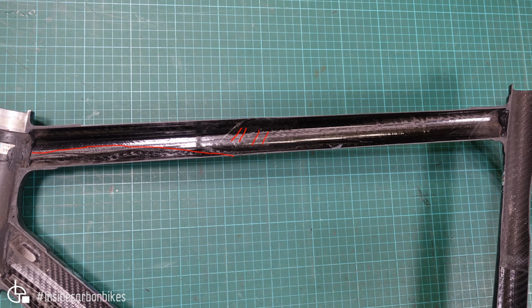In our experience, we see damage to the top tubes. That's the main damage that we see on these bikes. We don't often see damage to other areas of the frame. It's mainly the top tube, and whether they're using a different resin system, a non-toughened system, or whether it's a little bit resin rich or something like that, it just seems that the top tubes are a little bit more susceptible to damage than the other tubes on the frame. So a little bit unusual with that.